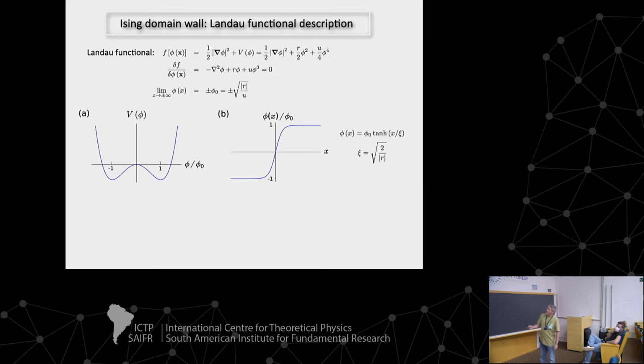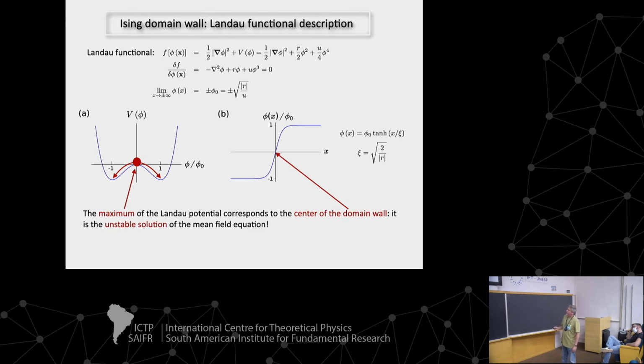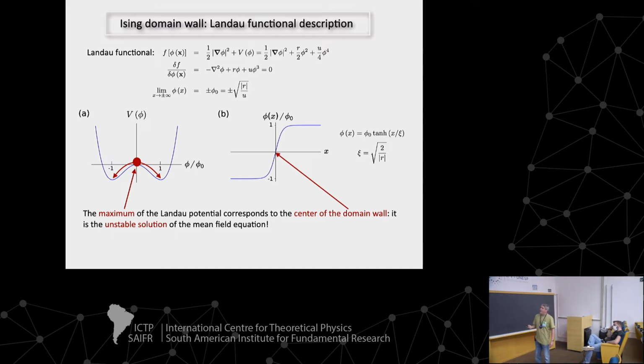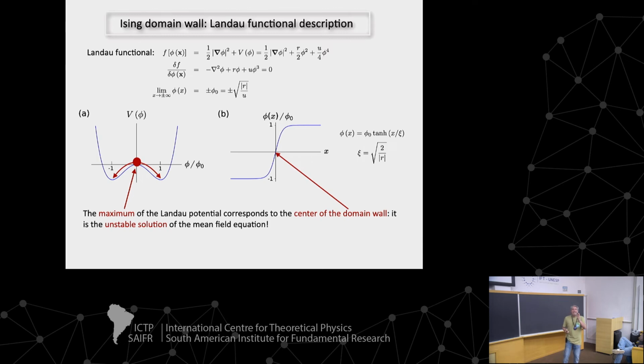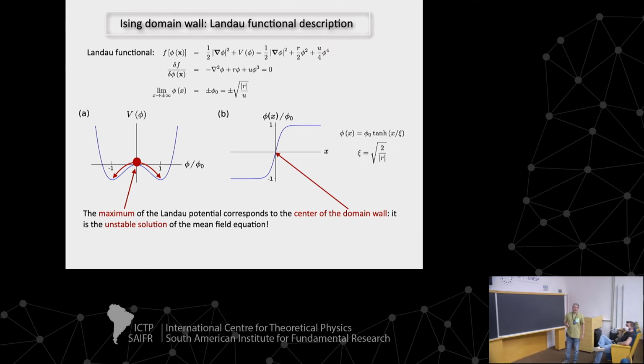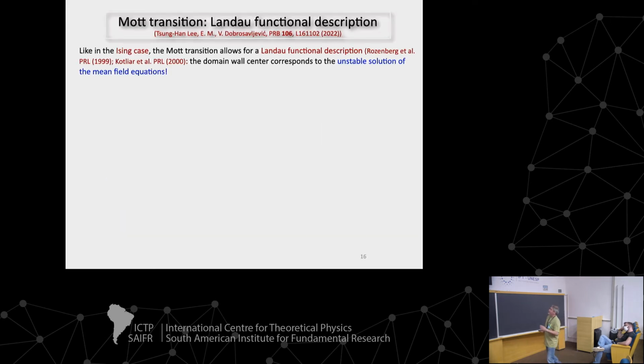This is one phase, the ferromagnetic phase, pointing down, pointing up. And if you cross from one to the other, the order parameter goes from -1 to +1. This is a solution of this equation. It's actually an analytical solution. And you have a domain wall between them. And the point that I want to draw your attention to is the following. The domain wall center is the maximum of the Landau potential. So the stable phases are the minima of the potential, but the domain wall center is the maximum. It's the unstable solution to the Landau functional equation. Okay? So bear that in mind as I go along.